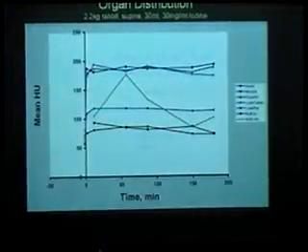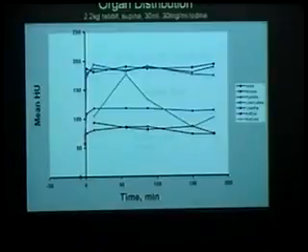All right, so now here is our data on iohexol. So this is an iodine compound that we have encapsulated in stealth liposomes. We put this in a rabbit. It's 30 mg per mil of iodine was the material that we made. We split the injection up actually into 2 injections that were 15 or 30 seconds apart, so it doesn't really show up on this plot, but you'll see the data later on.